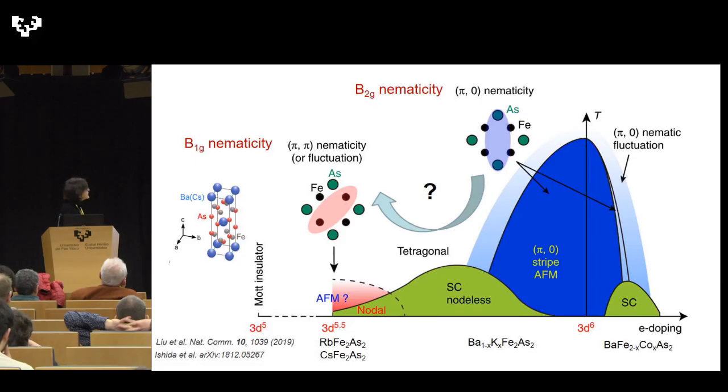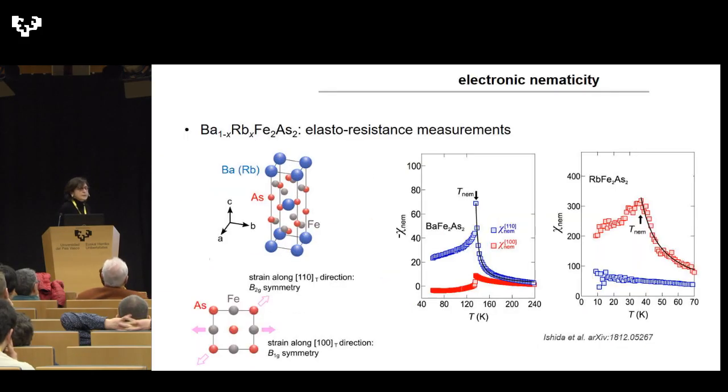And what was recently observed is, in fact, that the systems show nematicity and nematic order, which is not the nematic order that I was just presenting to you, considering these two interpenetrating Néel lattices. And the question is, why is this happening? What is the origin of this nematicity? Here we don't have a reference antiferromagnetic order to understand where these nematic fluctuations could come from. And this is, in fact, the experiment, just to show you that, since the title of my talk is strain effects, this nematic behavior is always observed when you strain the sample.